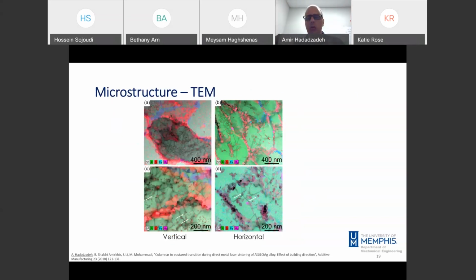Now let's take a closer look at the structure of the material using TEM. So far, we explored the cell structure and grain structure. Now let's take a closer look at the other features. Here you see the STEM or scanning mode of TEM microstructure, and the EDS elemental maps are superimposed on the STEM microstructures. The red region shows the silicon. So those walls or the boundaries of the cells are eutectic silicon walls, as for example, we can see them here and here. So these are eutectic silicon walls, and inside the aluminum matrix, we see two more features.